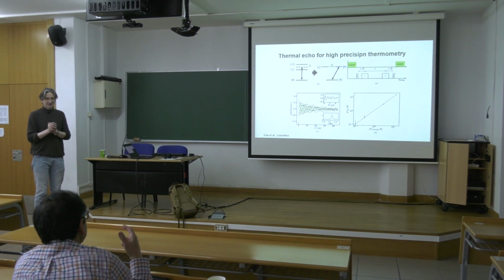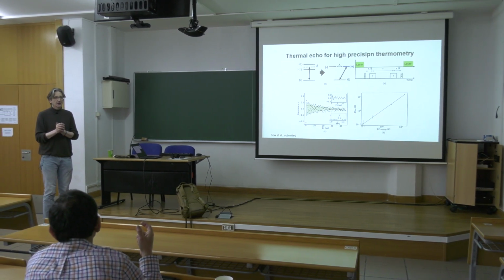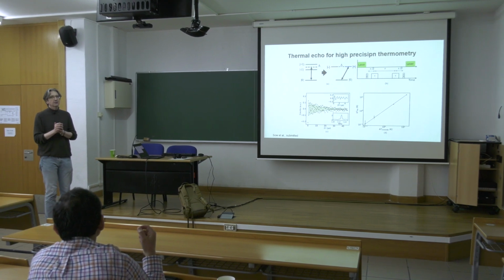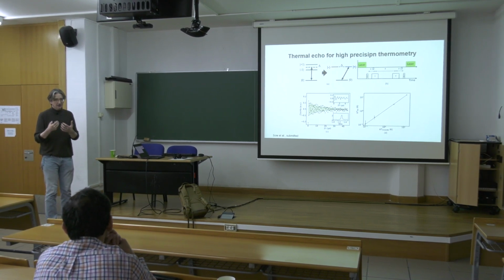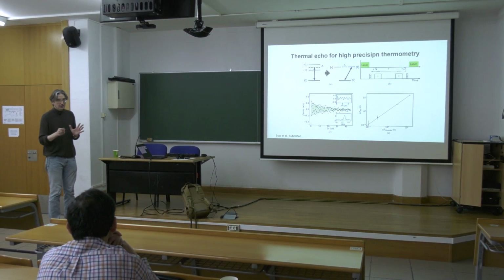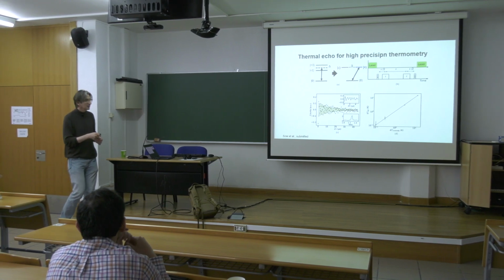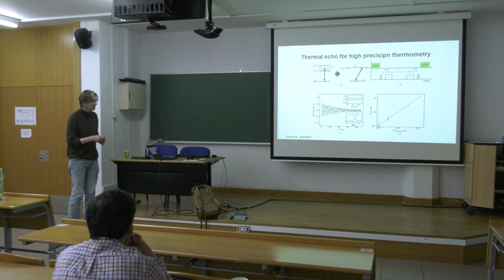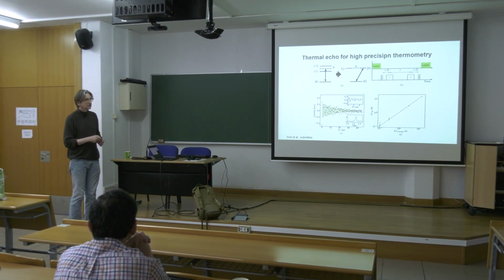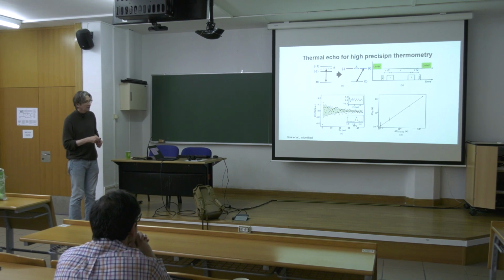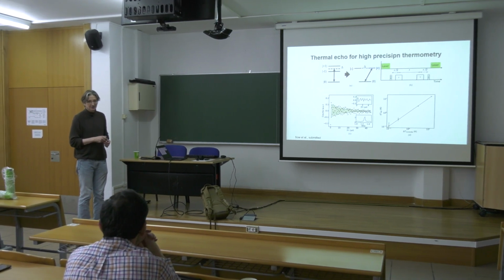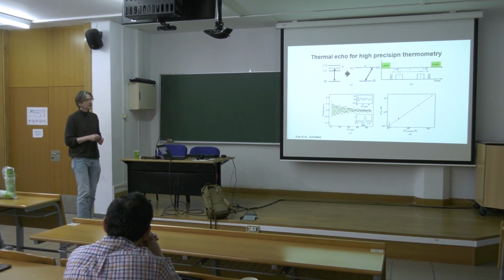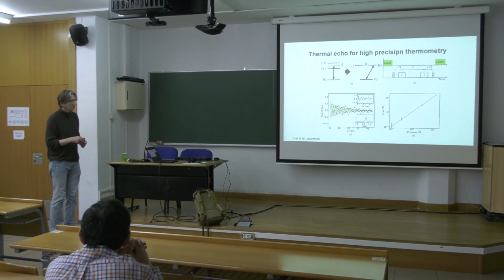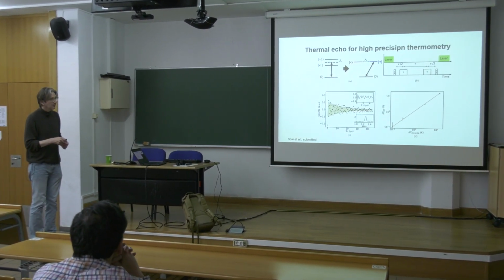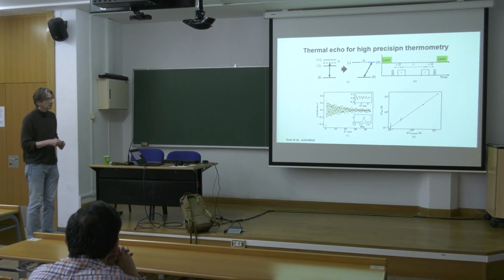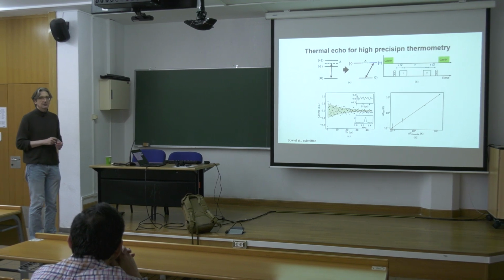So that was the question. So you need to measure both. You need to measure both. For example, in the simplest way, in this way, or you need to make a pulse sequence that cancels the delta and doesn't cancel this splitting. So this pulse sequence, which we call thermal echo, does exactly this. It basically cancels the effect associated with the splitting between -1 and +1, but doesn't cancel the effect associated with 0 to the center.